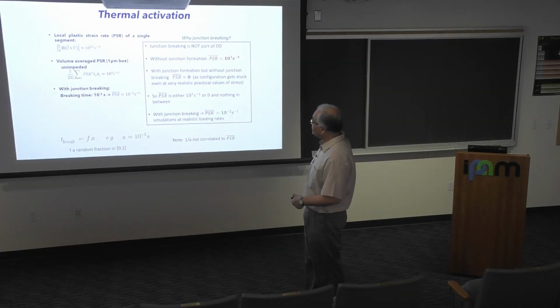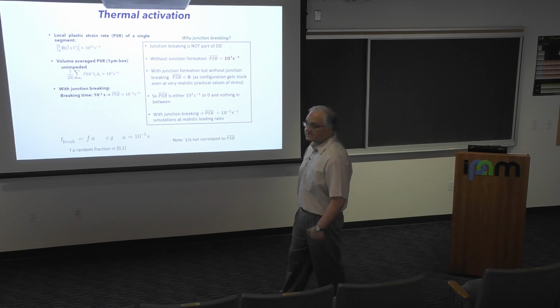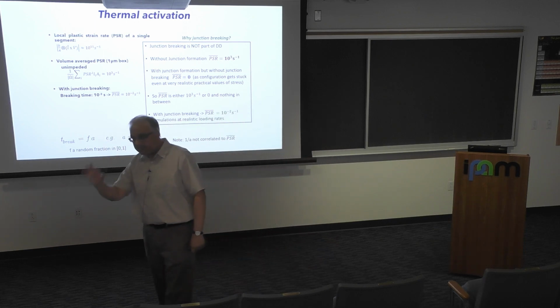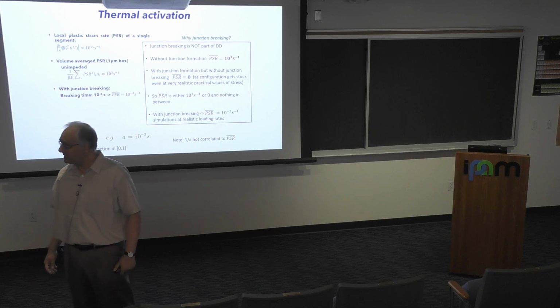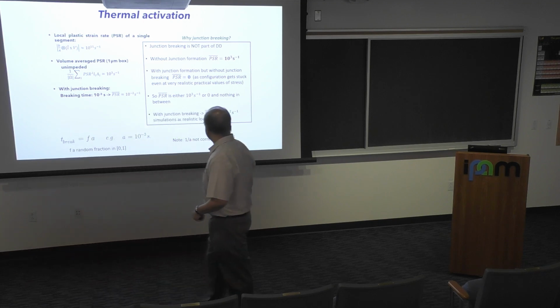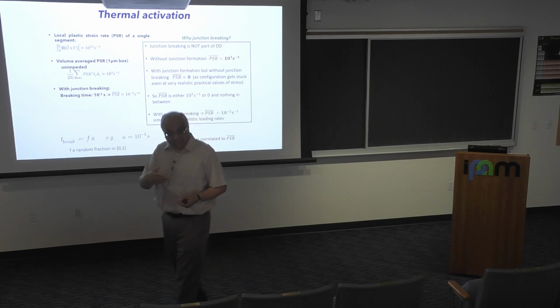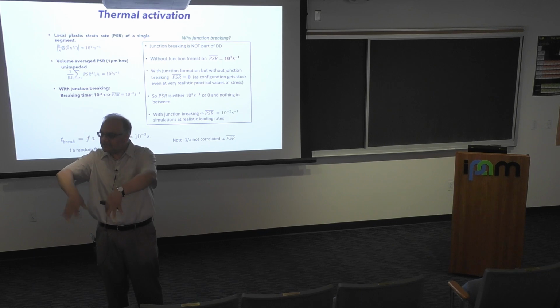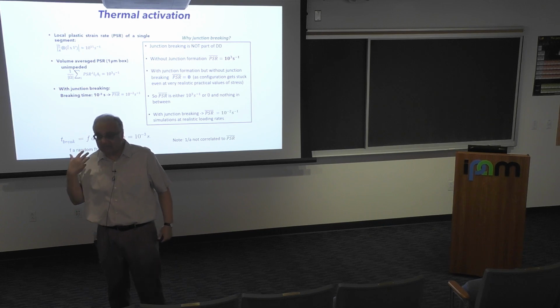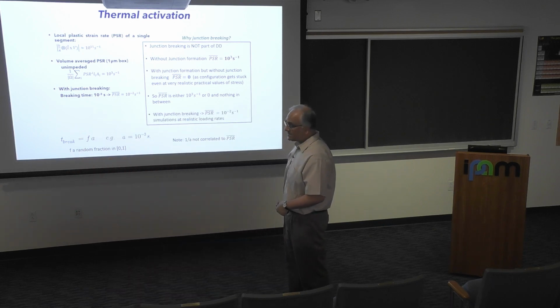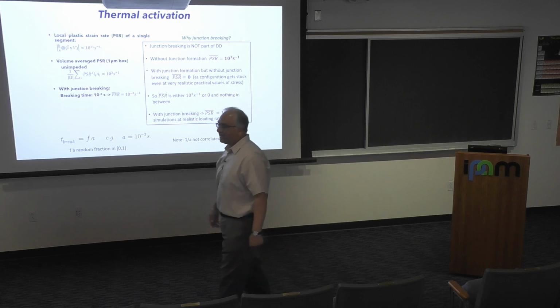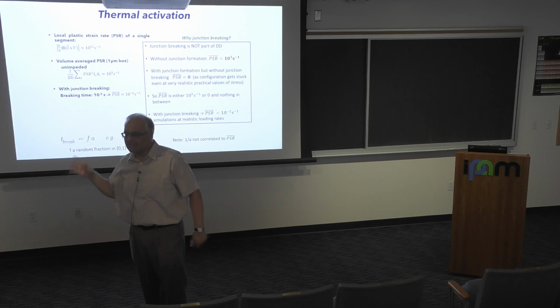Junctions have to form to get this small, but without junction formation, you have a very high strain rate. But if you form junctions and you do nothing else, strain rate will be 0 for the stresses that you want to see something at. So what are you going to do? The issue is what happens in reality. In reality, there's thermal activation, so dislocations can actually move past these obstacles, right? This is not part of the microscopic model we are talking about. So we made a model. Once you understand that, you draw this randomly in 0 to 1, and then there is a breaking time, which is 10 to the minus 3 per second, and junctions break like this, right?